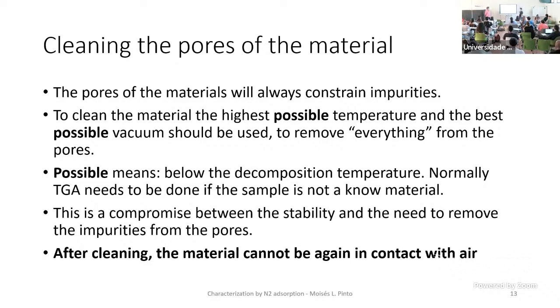In some materials, the impurities that you have are sometimes very hard to remove. For instance, if you are doing synthesis of some hybrid materials in solvents, the solvents may have a very high boiling point and sometimes it's difficult to remove. One strategy is to try to wash them first with a more volatile solvent. Then you have impurities of lower boiling point, and this will be easier to remove with temperature. After cleaning, you should not, of course, put the material back in contact with air, otherwise it will completely contaminate the material.